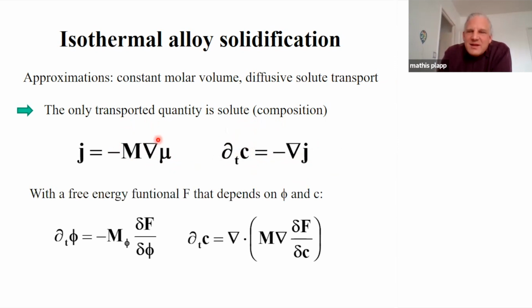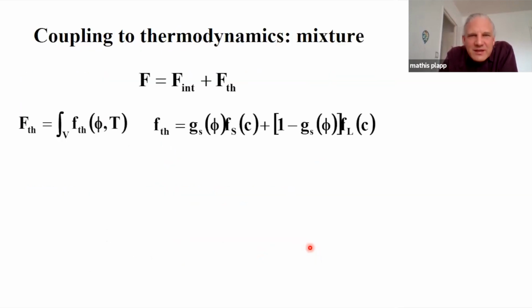Okay. And now suppose that I want to write down a phase field model. And now instead of on the temperature, the free energy densities of the solid and the liquid will depend on the composition. And so the variables of my functional f will be phi and c. And so for phi, I will write the same relaxation equation as before. But for c, I need to take into account this conservation law. So I take the divergence, I write the expression for the current, and the only thing I do, I will replace mu here by the local functional derivative of f with respect to c. And this is exactly how the first phase field models for alloy solidification were written.